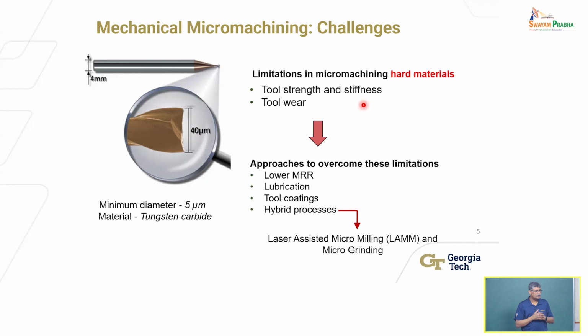Now, what are the approaches to try to overcome these challenges? Especially if you're trying to produce these features in difficult to machine materials, like I mentioned, titanium or ceramics for that matter, sintered ceramics. And we'll talk about that as well. And so one approach is to lower the material removal rate. I'm going to reduce the feed speed and depth of cut. That's one way to reduce forces and extend the life of the tool. But obviously that's counter to what you would like to do in practice. You want to produce the feature as quickly as possible, not as slowly as possible, unless you have no choice. Lubrication is another way.